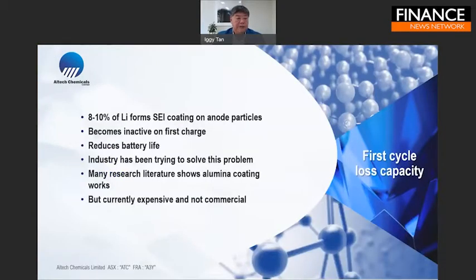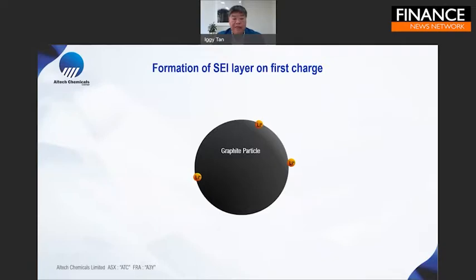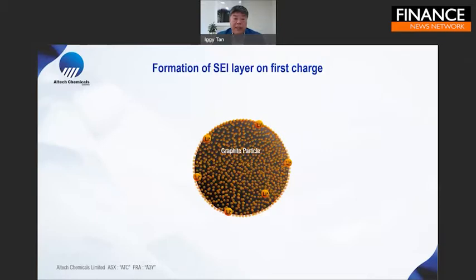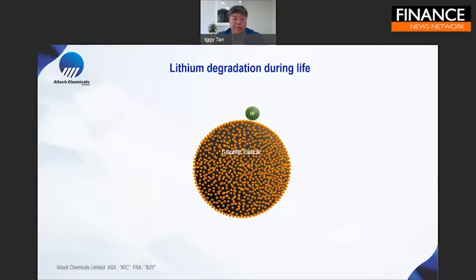Essentially, this has been a problem facing the industry, and people have been trying to resolve it. There's much research that shows that alumina coating works well to prevent this SEI layer from forming. But currently, the alumina coating technology is very expensive and not commercial. If we explain what happens at a particle level, the lithium forms this SEI layer around the graphite particle, and it becomes inactive to the future performance of the battery.